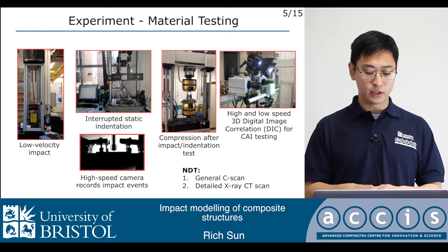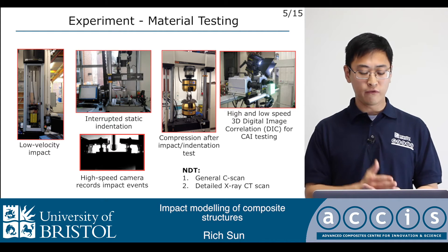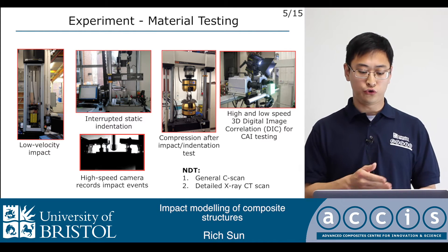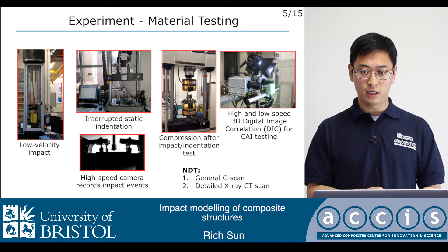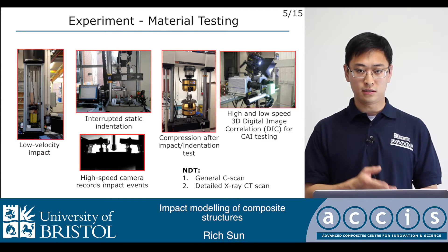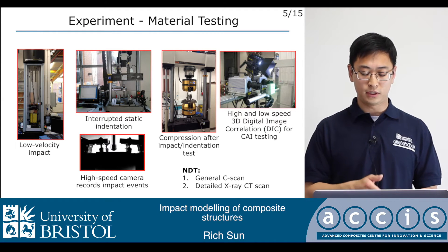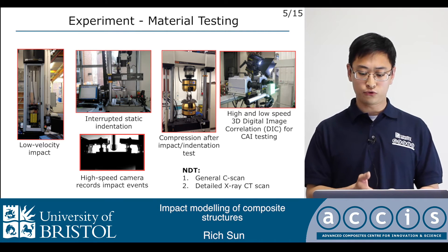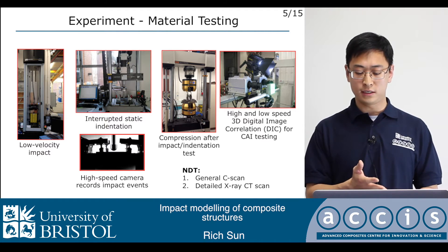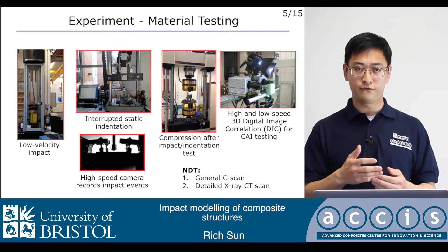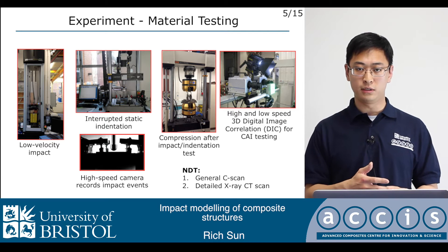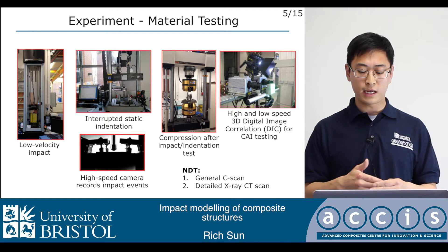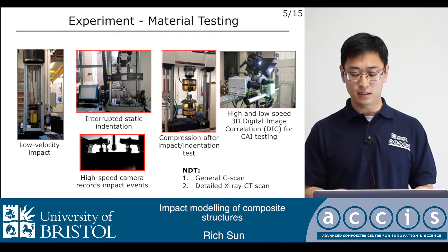These are the tests we performed during my study. We used low velocity impact tests and interrupted static indentation tests to introduce impact damage inside specimens. We then placed specimens into a compression after impact rig with three 3D digital image correlation (DIC) systems to capture full field displacement during compressive failure, and damage was assessed by C-scan and CT-scan.